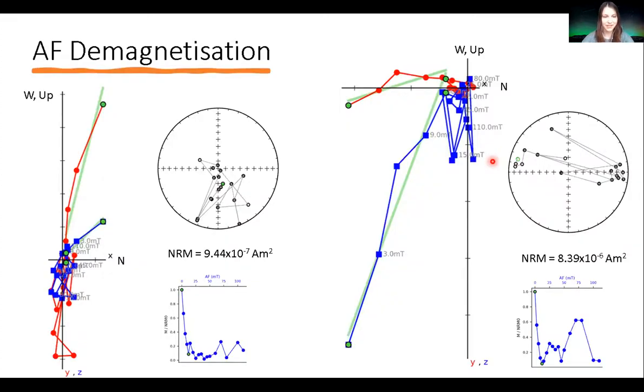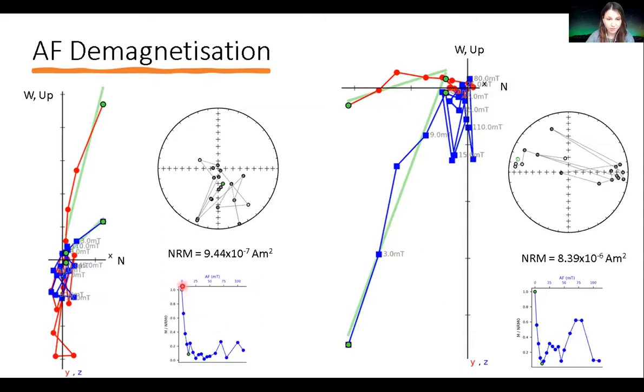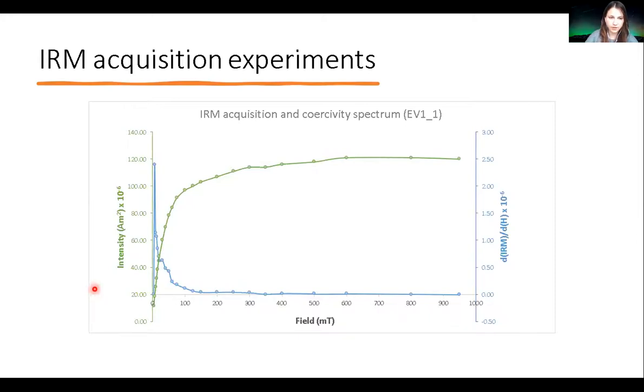I started the magnetic part of the study with bulk measurements and got these results. I apologize if the slide triggers some kind of fight-or-flight response — I'm told these plots are quite common in meteorite studies. What we see in both samples is a low-coercivity component which demagnetizes by 12 to 15 millitesla, and there is no stable high-coercivity component on top of this. The low-coercivity component contains most of the NRM, so essentially the high-coercivity spectrum just doesn't have any helpful information.